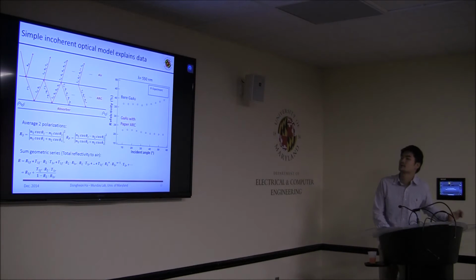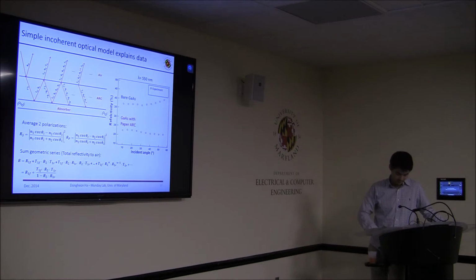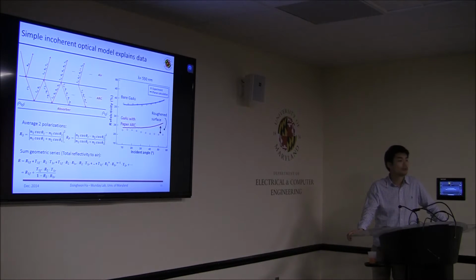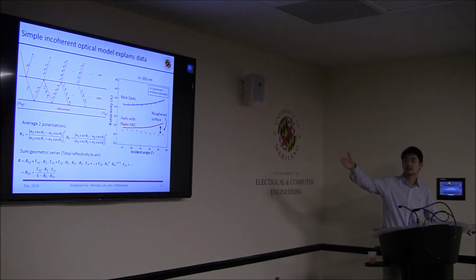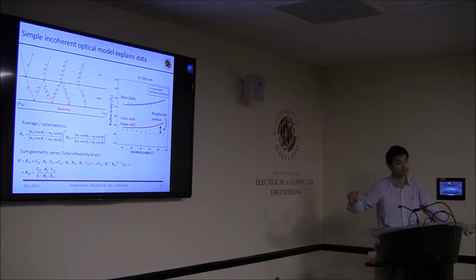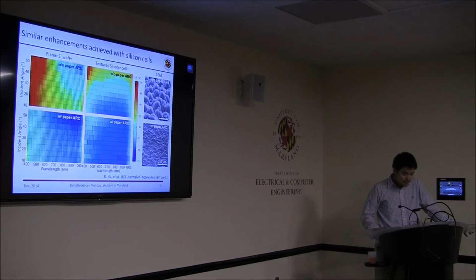If we apply that model to our measured data in the right figure, we know that for the bare cell, our model estimates the measured experimental data very well. However, for the case with the cellulose paper, our model overestimates the measured data. That is because this model is just based on the difference of the refractive index, so it doesn't contain the effect from the scattering. That's why our model overestimates the reflectivity. So we understand the physical origins of the enhancement: it is the combination of the change in the refractive index and the scattering effect.